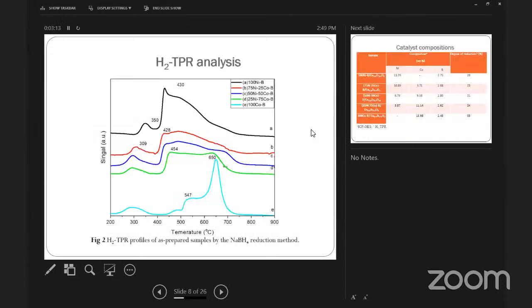These are the results. First we evaluated the reduction of the catalyst by using H2-TPR. Here we can see that by the addition of NaBH4 in the catalyst, there was a reduction of the catalyst, but not 100%. There is some consumption of hydrogen during the H2-TPR, but for the bimetallic catalyst it is lesser compared to the monometallic catalyst, especially for nickel and cobalt.